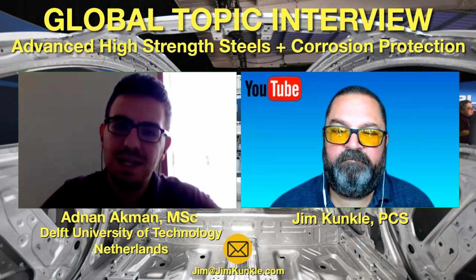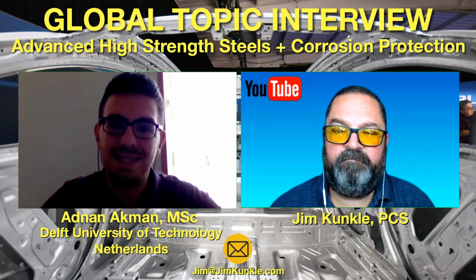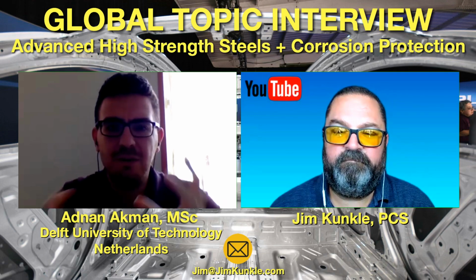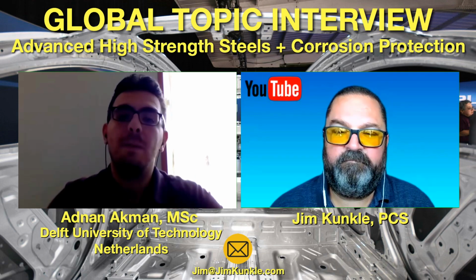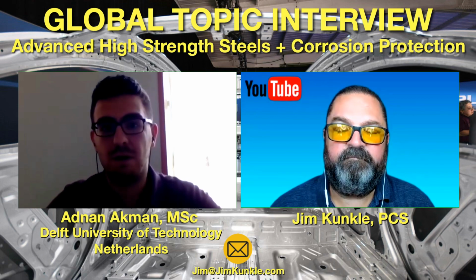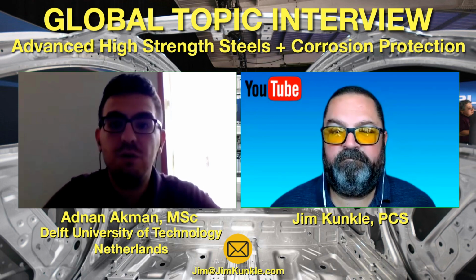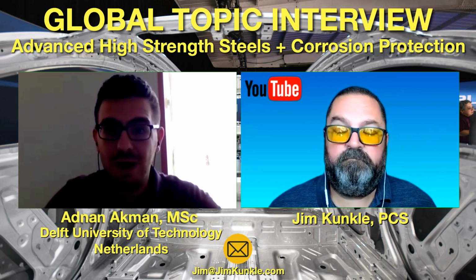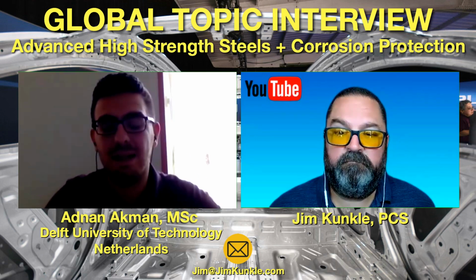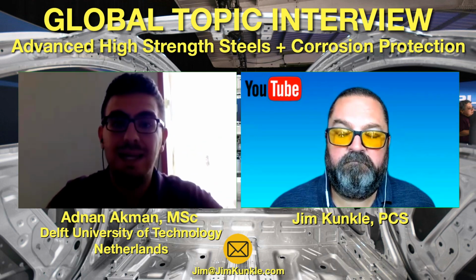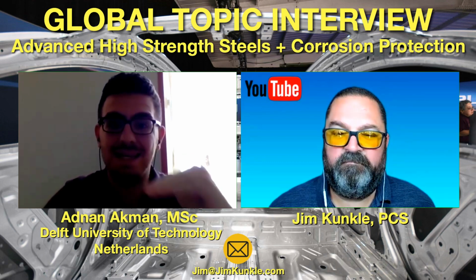In the induction heating system, your zinc coated steel passes through the induction system. It will liquefy, and there is an iron source close to the induction system, and iron will diffuse into your layer. So your final coating is a zinc iron alloy. Instead of pure zinc, in galvannealing, your coating is a zinc iron alloy.